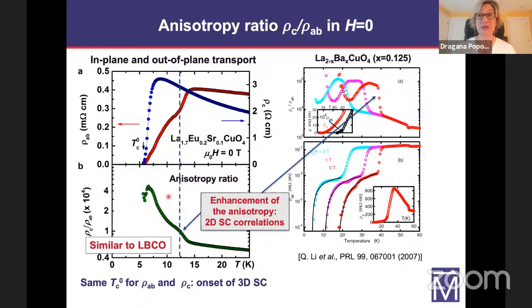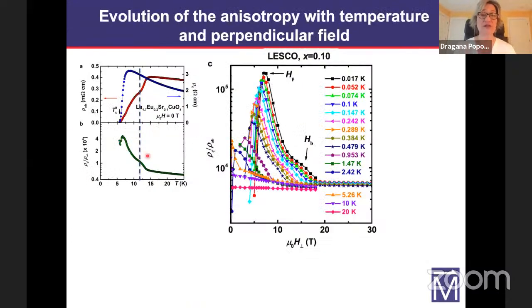Here we want to go one step further and actually study the evolution of this anisotropy first with a perpendicular magnetic field as we go through our phase diagram. So here on the left, these are the zero field data for comparison. On the right, in the main plot, we have the anisotropy ratio as a function of perpendicular field at different temperatures. So at high temperature of about 20 Kelvin, we do not see any field dependence, which is what you would expect because we are in the normal state.